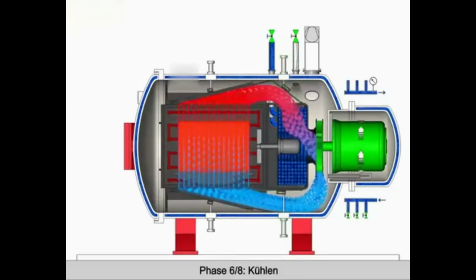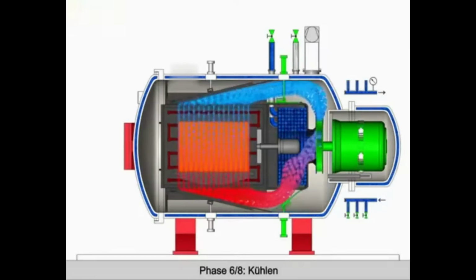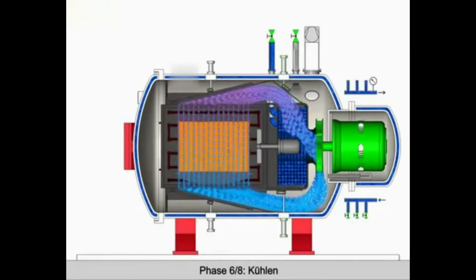How loaded up the furnace is will also dictate the quench rate. If many blades are stacked with each other, that increases the volume, and thus it takes longer to cool down. You can easily imagine how a 4-inch thick block of steel takes longer to cool than a 1/8 inch blade. And if a relatively small number of blades are in the furnace and they are well separated, that will mean a faster quench rate even with the same pressure quench. The heat treaters usually want to load up the furnace as much as possible for efficiency.